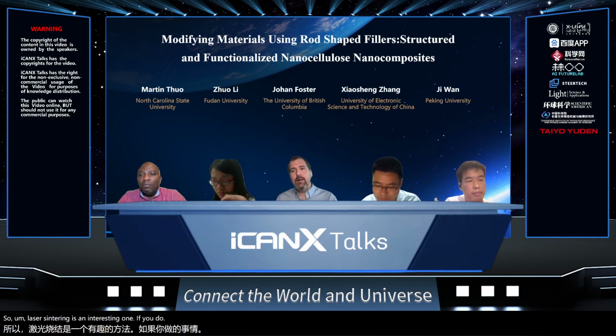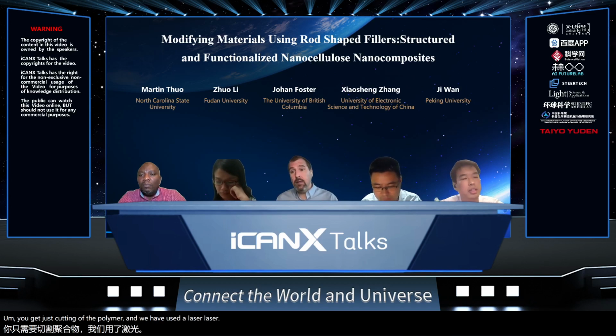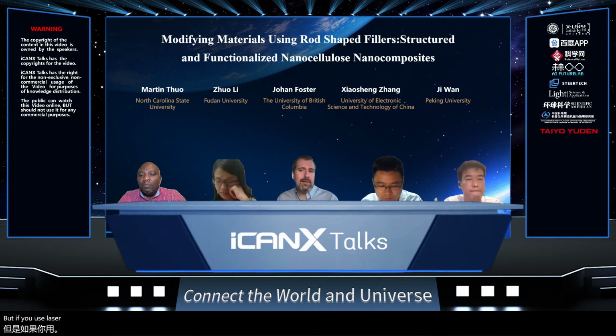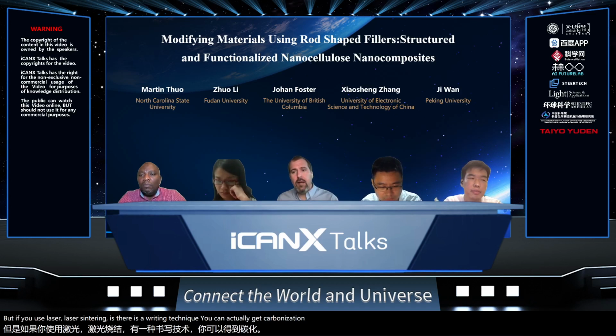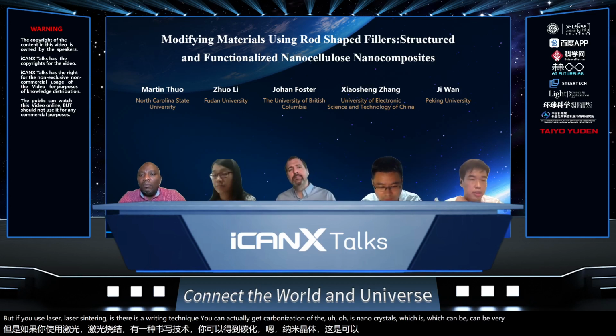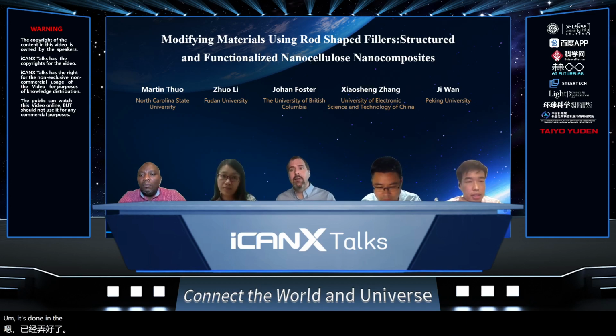If you do that in the right way, you get just cutting of the polymer, and we have used laser cutting to cut out our composites. But if you use laser sintering as a writing technique, you can actually get carbonization of the cellulose nanocrystals, which can be very interesting if done in the right way.